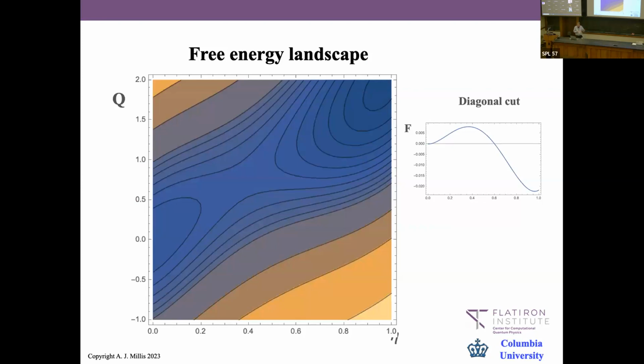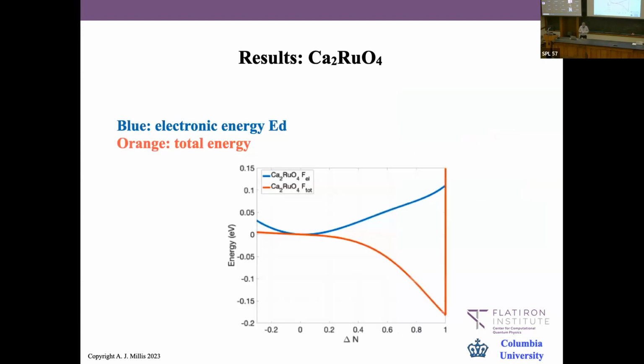Just as a sidebar, there's an interesting complication on top of that where our numerical methods fail. Spin-orbit coupling is not negligible in this compound. You made two orbitals to make a spin 1, and they also have an L equals 1. In fact, the ground state is J equals 0. There's interesting phenomena associated with getting a magnetic state out of something where the atomic configuration is J equals 0. But, okay.